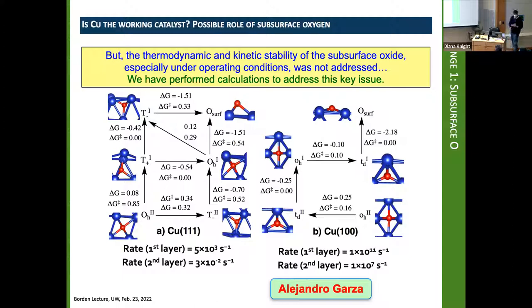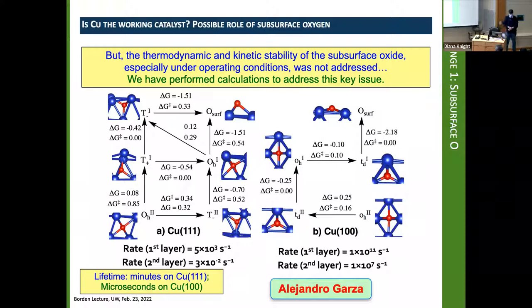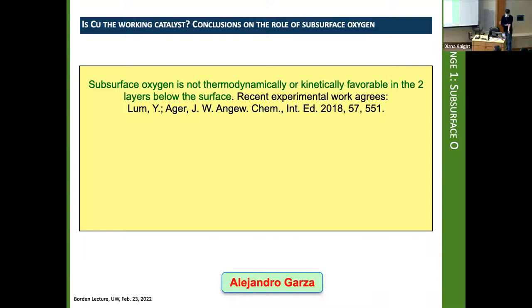The experiments that were looked at to address the question of the suboxide were not in situ, they were not operando experiments. Rather, the catalyst was removed and placed in the XPS instrument. And in fact, what we find is that the lifetime of a suboxide in situ conditions with applied bias is minutes on copper 111, and we predict microseconds on copper 100. So this in fact favors the Occam's razor suggestion that the simplest catalyst is indeed the one we should think about, that the active catalyst probably can be copper. Suboxides are not thermodynamically stable. So there's also some recent experimental work that suggests subsurface oxides are not either thermodynamically or kinetically favorable.